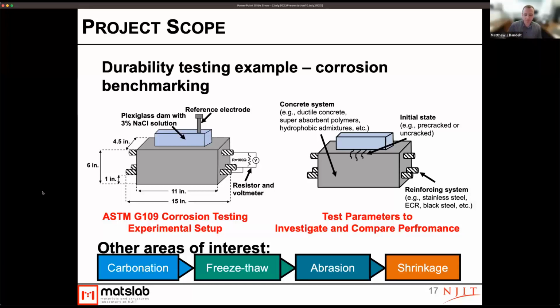And then in terms of some of the things that we looked at changing, like the concrete system itself, we looked at the different fiber reinforced concrete systems that I presented on the last slide. We looked at a few standard New Jersey Department of Transportation systems as well. We also looked at the initial state of the system, whether it was pre-cracked or uncracked. And specifically what we're interested in is, if you were to get some initial cracking, whether it be from mechanical loading or shrinkage or whatever sort of effects that you might have in a real system, how does that influence the long-term durability? So if you get cracks in whether it be a traditional concrete or one of these new systems, how will that influence long-term corrosion?